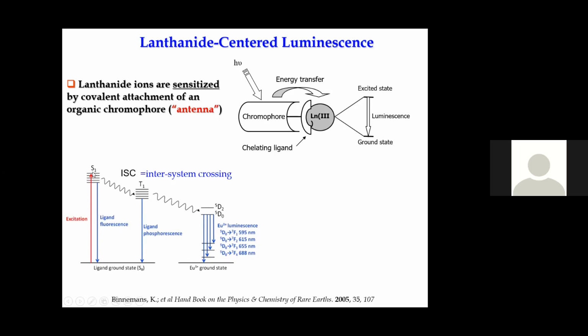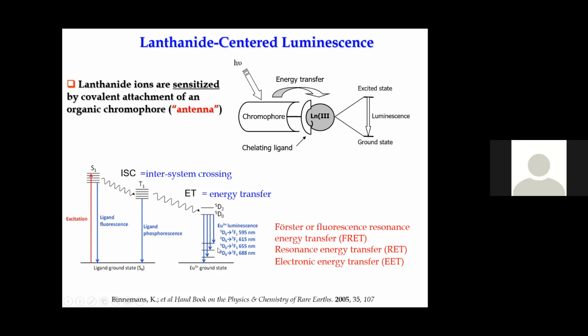We want it to get excited, and then we want that singlet energy to transfer to the triplet level. We call it intersystem crossing. And the triplet level, if it goes down, it's called phosphorescence. We do not want that either. We want that triplet energy to get transferred to the metal excited states. These are quantum numbers or excited states defined as term symbols. And that's called energy transfer from triplet to the lanthanide excited state. And when it comes down there, we see the lanthanide-based emission.